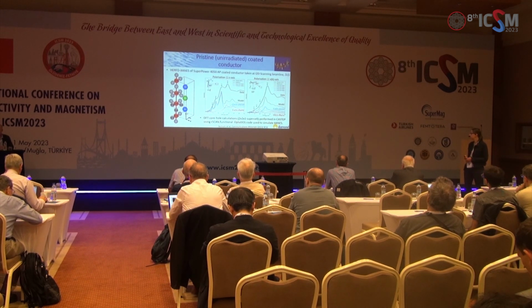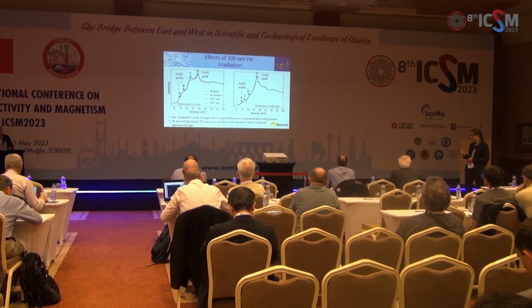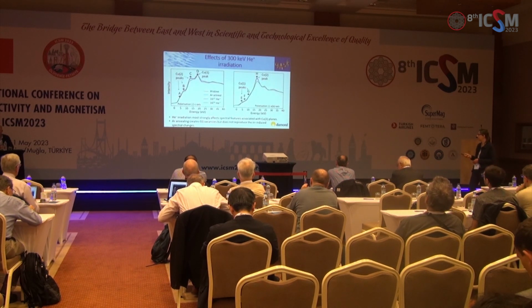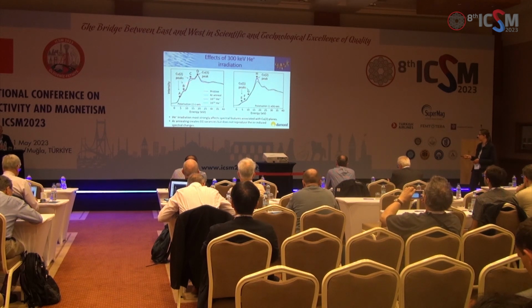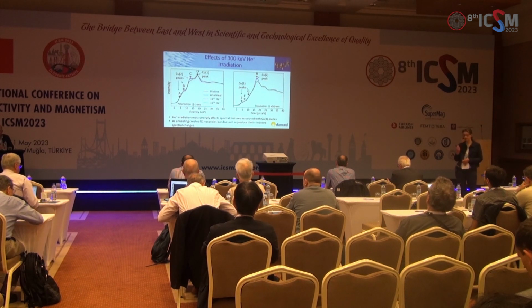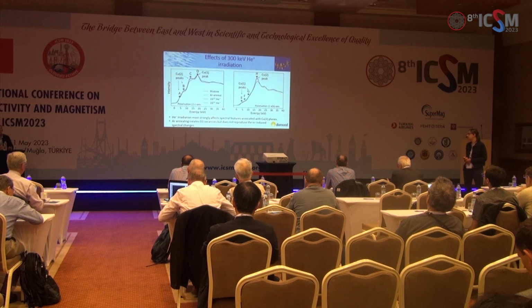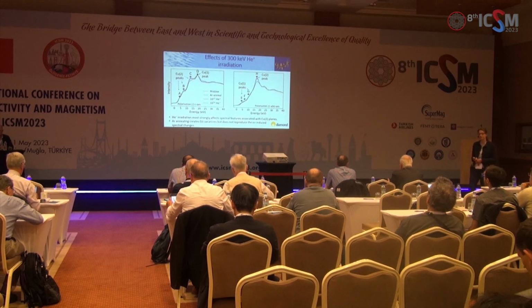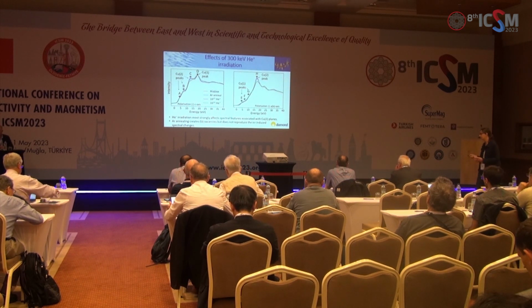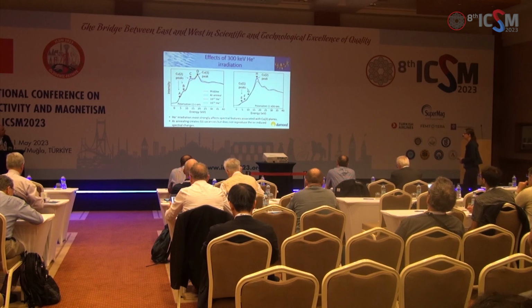So what happens when we do the irradiation? Well, there's various graphs on here, but essentially the pristine sample and argon irradiated and other things are shown here. They're all very similar, apart from the green one, which is a heavily ion irradiated sample. So it's the sample that I showed you the electron microscopy from earlier, where it looked like all the cations were still where they should be.